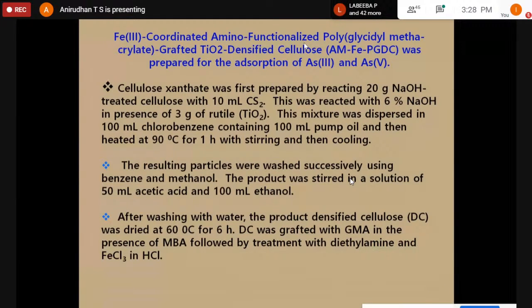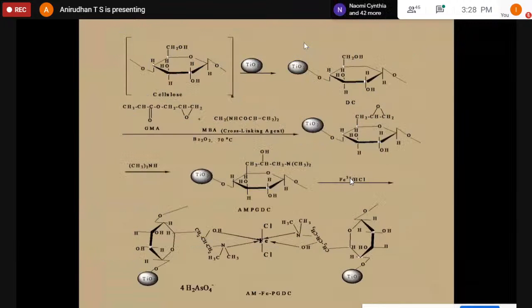Simply densified cellulose, because we have introduced both titanium and iron inside this cellulose, and we have encapsulated it with a polymer, and this polymer contains fingers or hands with different types of reaction sites. You see, this is very simple. We have cellulose extracted from plant material, and we introduce titanium. As I mentioned earlier, first you convert to cellulose xanthate treated with rutile, and we have titanium incorporated densified cellulose, and further react with a monomer, like glycidyl methacrylate with methylene bisacrylamide cross-linking, and your product has an epoxide ring.